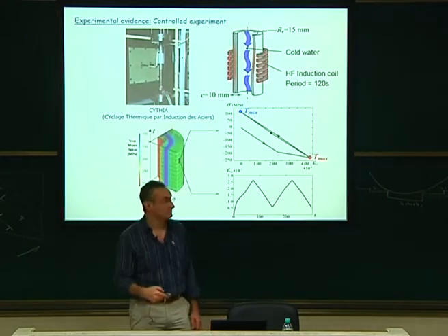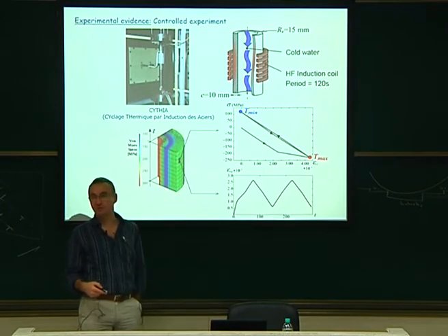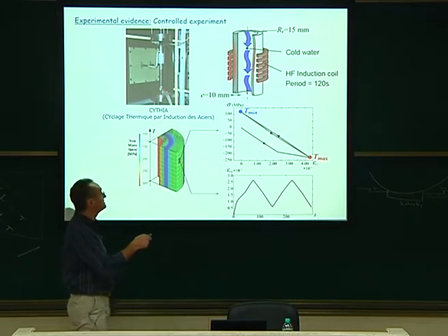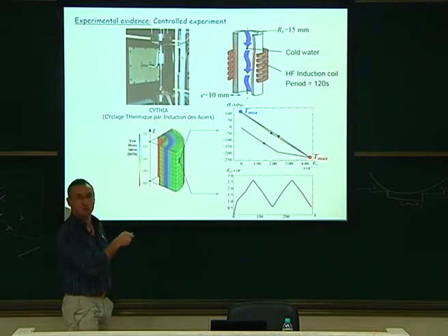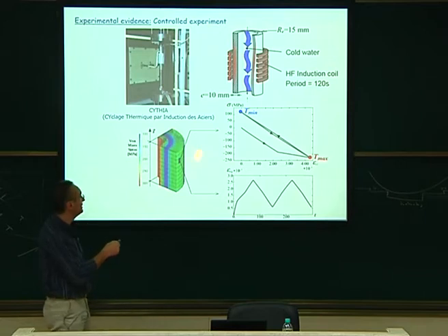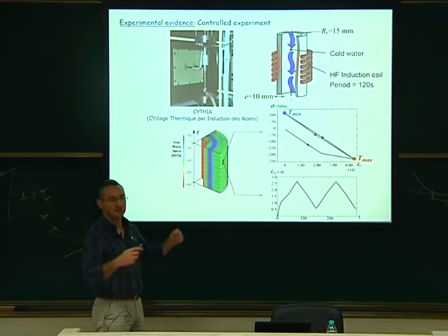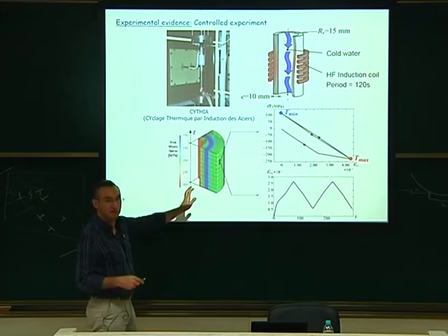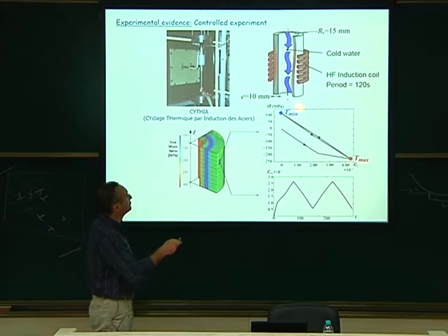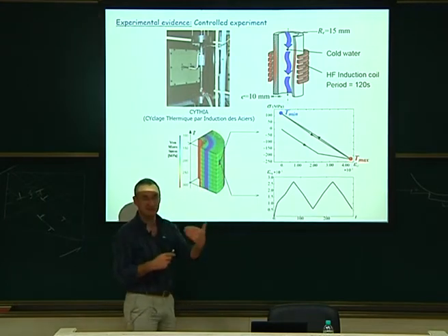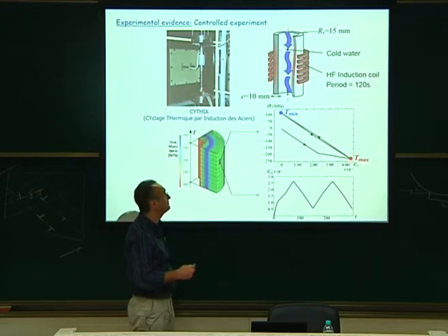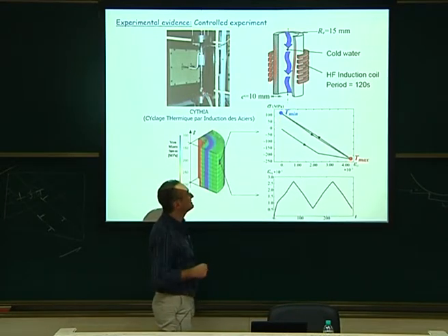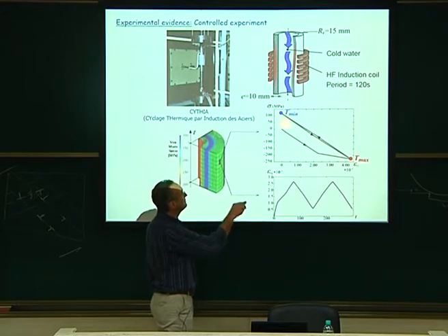And if you look at the stress that you have in your material during those loading conditions, it looks like that. You can use a simple FEM model, which was fitted on a stainless steel. This was a J2 model, by the way. It's not crystal plasticity, it's a very simple model. But it was nicely reproducing the tensile experiments and the cyclic experiments, so we are confident it works. And with that model, we were looking at the state of this node here, the first row of elements at the outer part of the pipe, when the temperature is minimum or when it is maximum. And you see this is the stress level, so it is oscillating. First you start here, and then there is a cycle here.